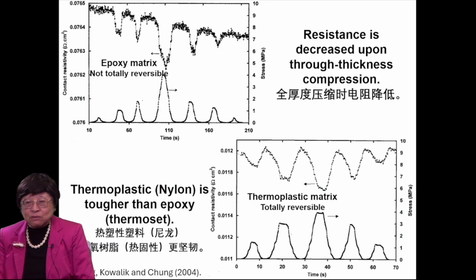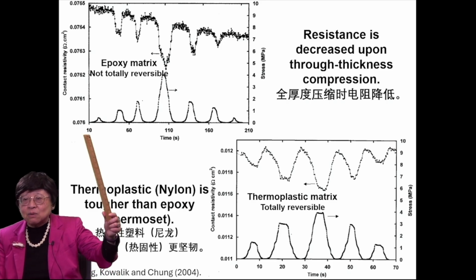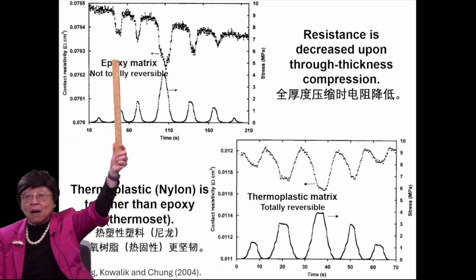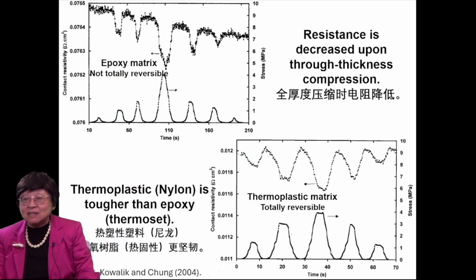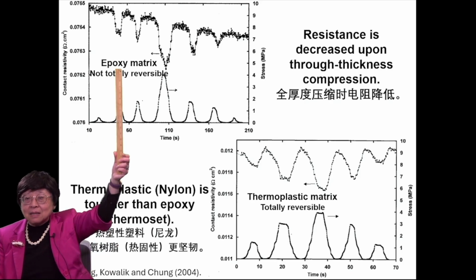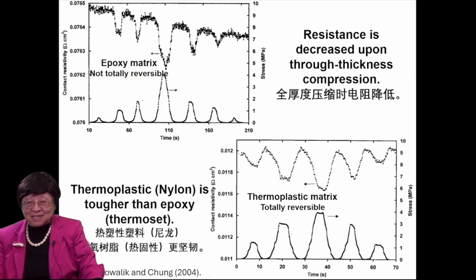So we can measure the contact resistivities during the squeezing. So here is squeezing at different stress amplitudes, and we monitor the contact resistivity of the interlaminar interface, and we find that every time one squeezes, the contact resistivity goes down, and that is because the squeezing increases the proximity between the adjacent laminae, thus increasing the fiber-fiber contact across the interlaminar interface. And so this contact resistivity decreases upon squeezing. But it's not totally reversible. And that means that the microstructure of the interface is changed irreversibly a little bit every time you squeeze.